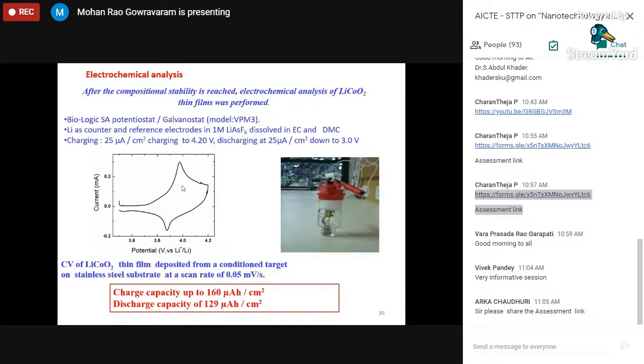So you perform an electrochemical study, which is also called a CV study. And then there is one oxidation peak and one reduction peak. That means it is electrochemically active. So the film gave a charging capacity of 160 microampere hour per centimeter square and a discharge capacity of about 130 microampere hour per centimeter square for a 1 micron thick lithium cobalt oxide film. That means your lithium cobalt oxide is working.